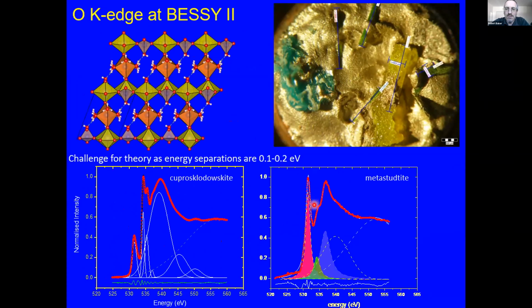Just to show you how these change compared to conventional K-edge spectra, we were able to measure cuprosklodowskite, which are these crystals, and this we bought off eBay. So there is a whole range of compounds you can buy off eBay, and this is the copper uranyl silicates. This was measured at BESSY and the normal K-edge data, and you can see that there's a bit more resolution in this compared to here. And Ping Yang at LANL is looking at the theory of these complexes. And again, the energy separations in some of these are 0.1 to 0.2 eV, so a challenge for theory.